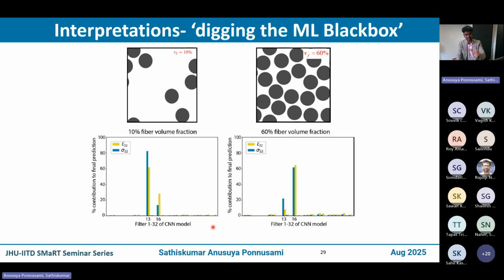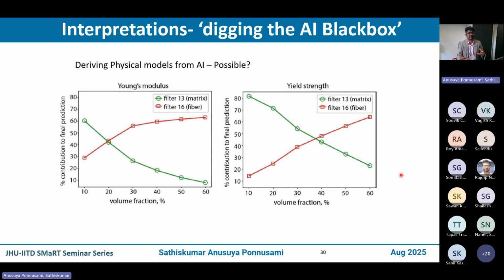Yeah. So as a third step within this interpretation process, we also looked into whether we can get some insights into the physical model that it is trying to learn, and that is the result you see here. The x-axis is the volume fraction of one of the phases, the fiber phase, and the y-axis is the contribution of those two features, the fiber and matrix phase. What you see on the left-hand side, the Young's modulus, is a nonlinear variation, which is what you typically expect in a transverse Young's modulus for a two-phase composite. Which means the physics is kind of learned during this process. That is revealed through this interpretation.